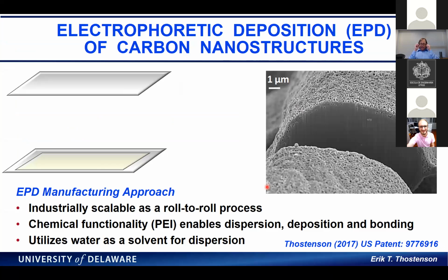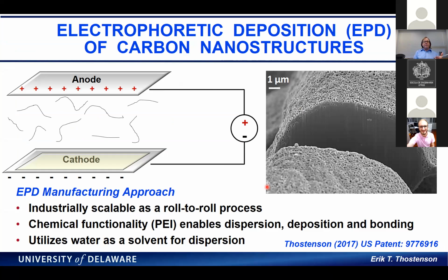But one thing, and this is a unique process that we've really developed in my lab, was granted a few years ago a US patent specifically for depositing on and creating these unique films on non-conductive fibers. This is what we call electrophoretic deposition. We take nanotubes, or other particles, we chemically functionalize them, and we disperse them in water. By controlling the chemistry, they have a charge, and what that does is it stabilizes the dispersion.